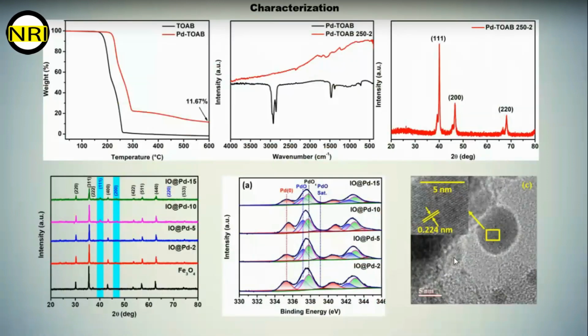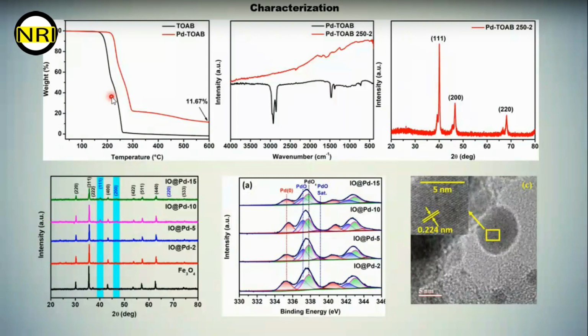I have done the TGA of TOABr and of the palladium TOABr. We can see that the TOABr decomposition temperature is 210 degrees C, and the palladium TOABr decomposition temperature increases to 250 degrees C because of the coordination of TOABr with the palladium. So as you can see, palladium TOABr decomposes at 250 degrees C.